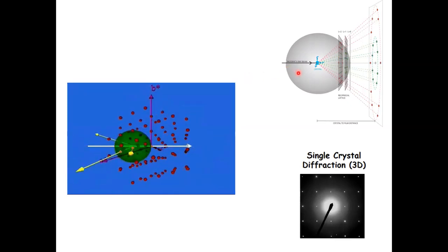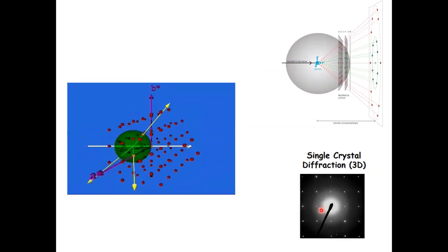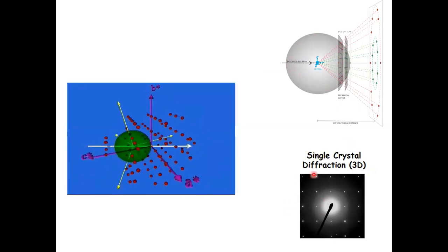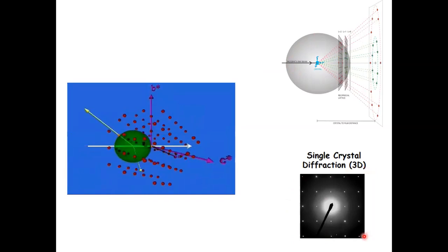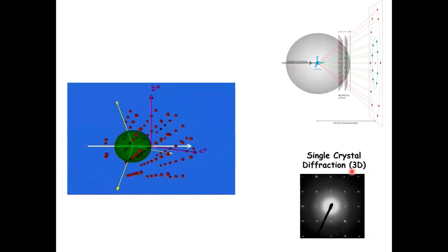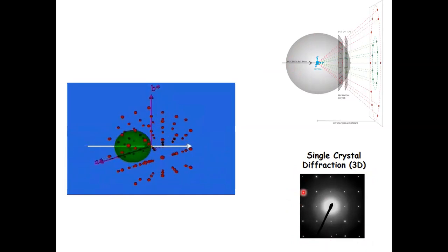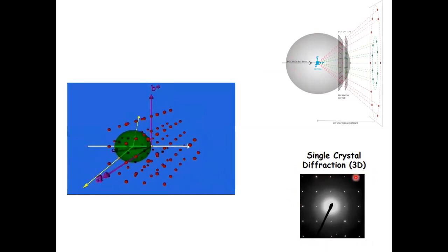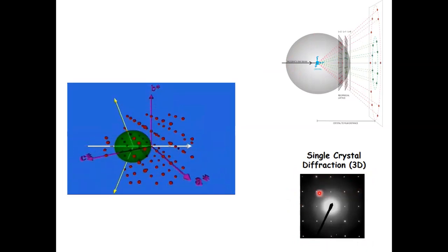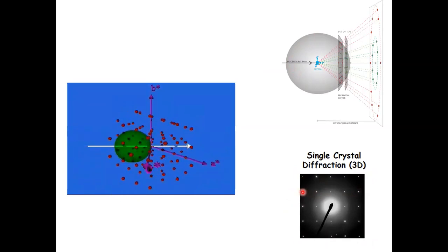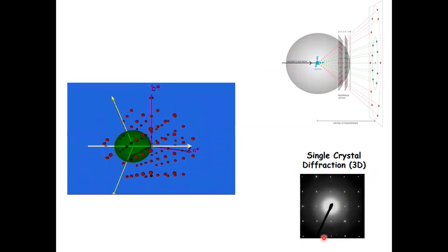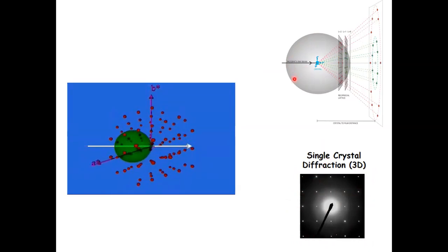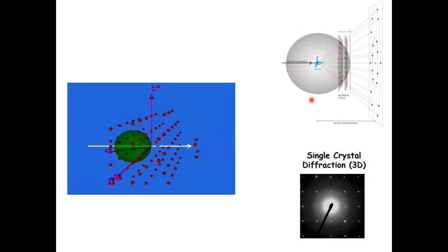All right, now you see here two other images. You see that when we actually place a photographic film behind a single crystal, whereby we do not move the crystal in this case, then we see here our diffraction spots. So these diffraction spots can be interpreted as nothing else but lattice points in the reciprocal space. Okay, that becomes now clear when we look at this image here.